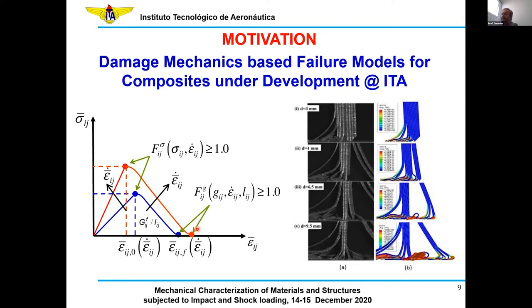And then later on, by using a sort of combined loading condition, we try to bring them together by using suitable specimens to build up a propagation failure criteria. This also applies for the initiation criteria, which is essentially stress-based. Therefore, most of the damage mechanics failure models that we have been working on use a stress-based criteria for damage initiation and energy-based criteria for damage progression. So we can use some advanced algorithms to control the dissipated energy associated with each failure mode, regardless of the mesh refinement, by using a sort of smeared cracking approach.